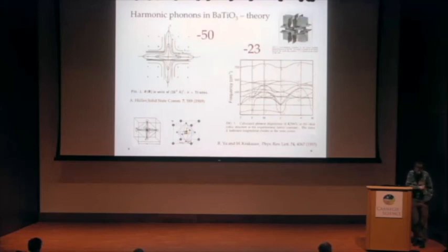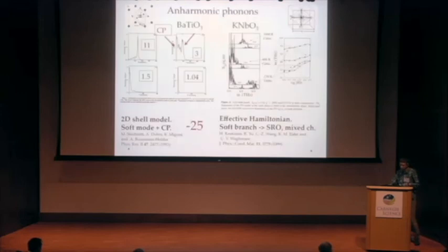by Henrik Krakauer and coworkers in potassium niobate, showing that there is not just an unstable mode at the gamma point, but in many other directions in reciprocal space, though not all. So this explains this anisotropy. That's more or less understood since a long time.